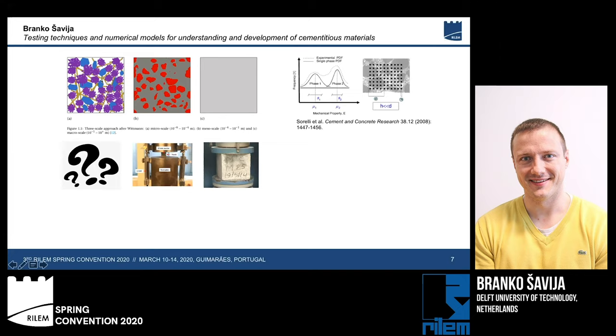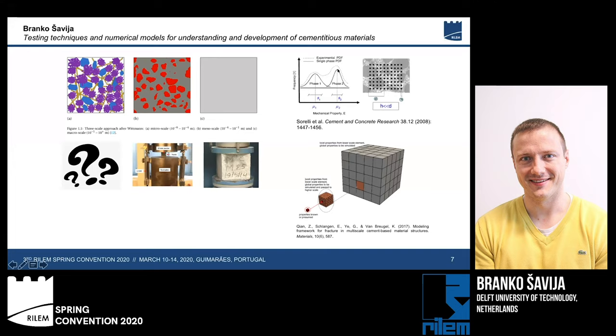Nanoindentation techniques have been used widely, and we are able to quantify the elastic moduli and the hardness properties of inner products, outer products, clinker, calcium hydroxide, and other phases in our cement paste. And then using analytical or numerical techniques, we can use homogenization to go from these properties at the micro scale, upscale them to the meso scale, and finally to the macro scale. And we can obtain elastic properties of cementitious materials using homogenization.